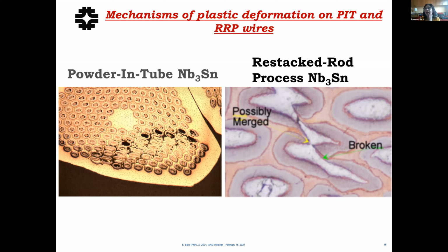And this was found out decades ago in the niobium titanium magnets, which are now used all over. I mean, any accelerator now in high energy physics is made of the prior superconductor, which is niobium titanium. And this conductor, niobium-3-tin, as I showed you, has a much higher critical field, and that's why it's now used for high field magnets. But it didn't work because of these magnetic instabilities due to this problem.